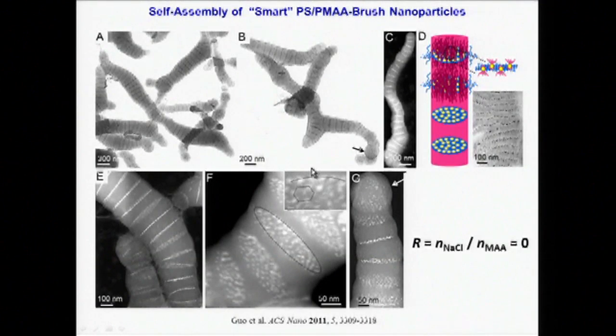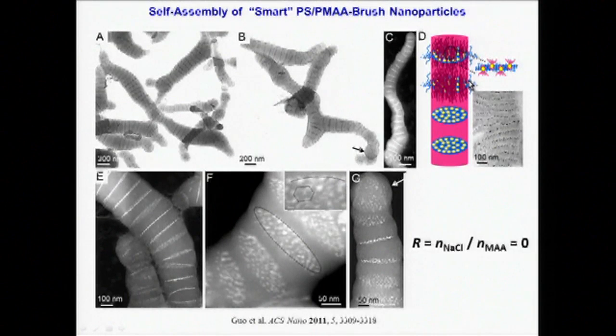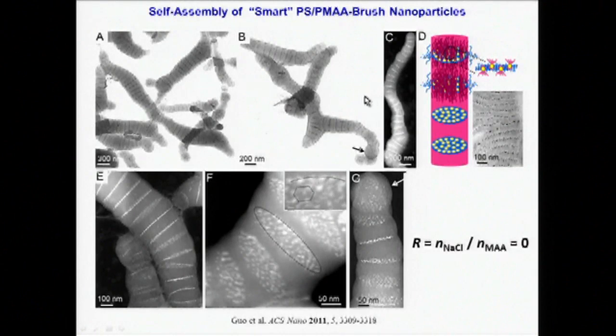One striking feature of these worm-like assemblies is that only the polymethacrylic acid blocks around the periphery of the quantum dots are solubilized in water, with the vast majority of hydrophobic chains preferring to phase separate from solution and incorporate into the internal structure of the worms.